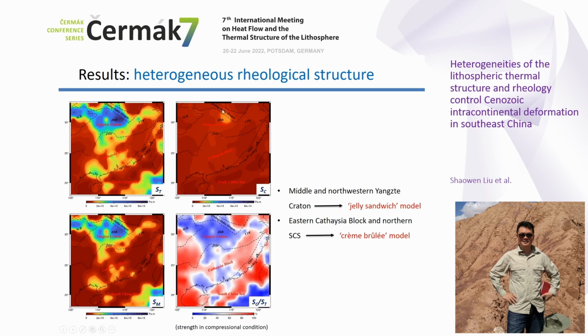Here, we give the stress distribution of the total lithosphere, the crust, the mantle, and the percentage of crustal stress to the total stress. We can see that the middle and northwestern Yangtze Craton has the highest stress. The fraction of the crustal stress is lower than 40% in these regions, indicating that most of the Yangtze Craton is of a strong mantle lithosphere, consistent with the jelly sandwich rheological model.